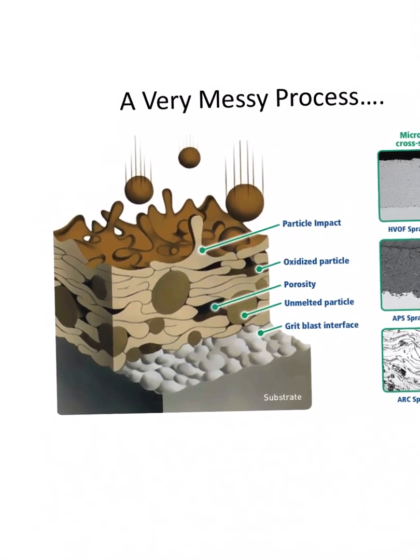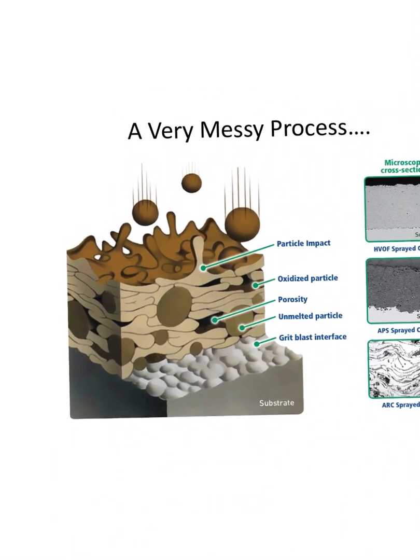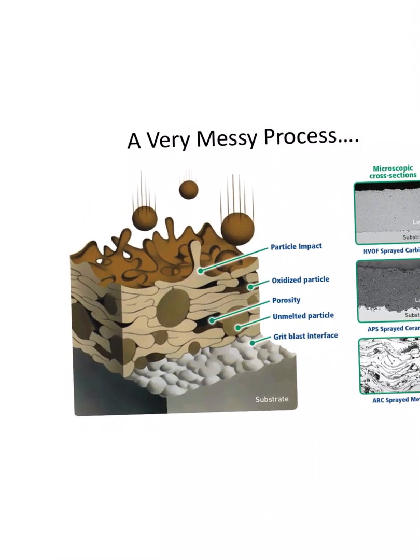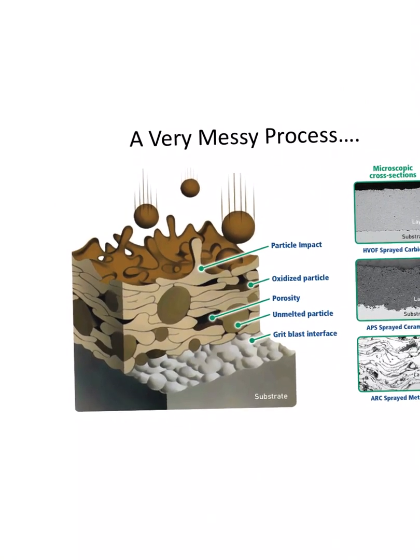All right, and so this is just showing you another version of that in which these droplets are making an impact. We have some evidence of, first off, it says grit blast interface, which sounds really crude, but is actually what they have used for many years for some of these implants. You take alumina, not sand, blast it with alumina, clean off that surface and generate roughness, and then this plasma coating can interact with it more efficiently, giving you that mechanical keying, that interlocking that you're looking for.